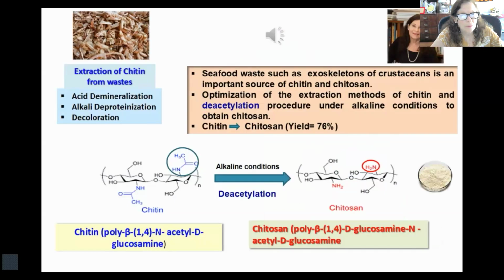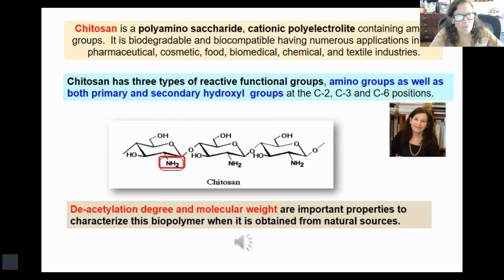Extraction of chitin from waste involves acid demineralization, alkali deproteinization, and decoloration. We work on the optimization of the extraction methods of chitin and the deacetylation procedure under alkaline conditions to obtain chitosan. The yield in this last step was 76%. Chitosan is a polyaminosaccharide cationic polyelectrolyte containing amino groups. It is biodegradable and biocompatible, having numerous applications in the pharmaceutical, cosmetic, food, biomedical, chemical, and textile industry.